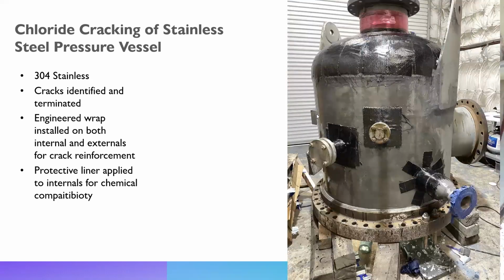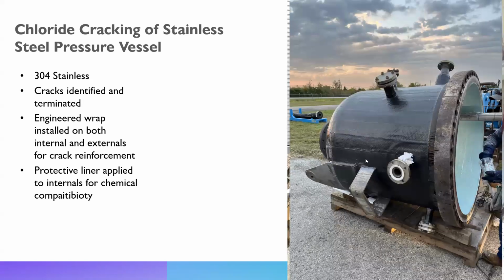As you can see, the pressure vessel has several nozzles, so you do need some techniques to go around the nozzles. And then we also installed a protective liner on the inside. It did have HCl on the inside, which is probably where the chlorides were coming from. So it had a small percentage of HCl, and it also had some alcohols and ketones. Pretty aggressive process, at elevated temperatures operating above 250 F. So we went with our high temperature liner and our high temperature resin with our carbon fiber to do the pressure retention.